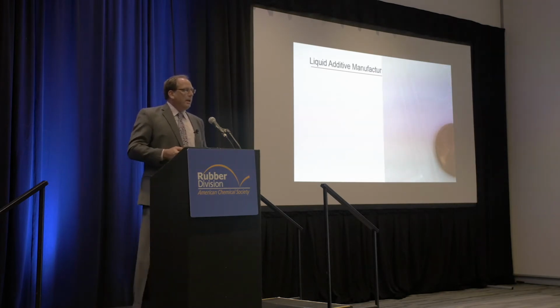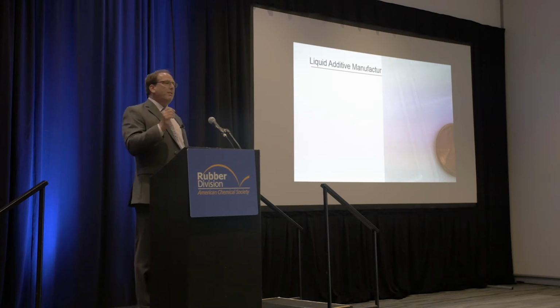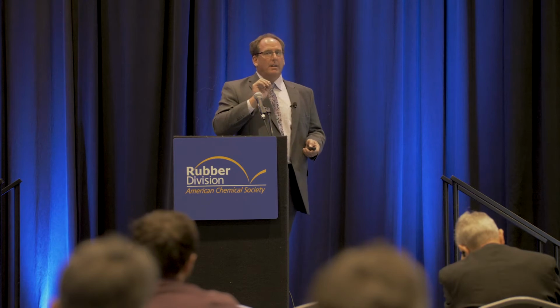And really, when we look at the size of the bead and the shape of the bead, we control that with unique viscoelastic properties of the material. I said I'm bringing to you both a machine and a material. Can any LSR be used? It's often asked. Well, yes, but you won't have the printer definition, because we have to have the chemorheology of the material as well as the viscoelastic properties very well pegged and very much related to the software. So not every LSR works very well. And so we learned that very early on in this work, and so we've developed both those, material and machine, together.